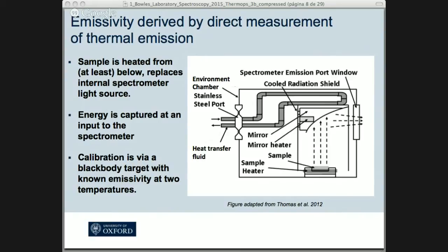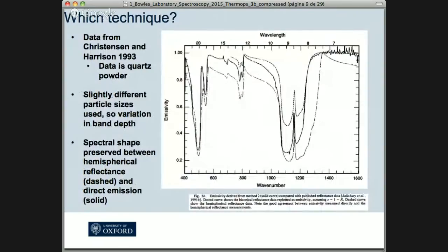And you control the thermal environment very accurately by having a temperature-controlled thermal shield around it to calculate out the downwelling radiance, and they also calculate the instrument response function using two temperature black body targets of known emissivity that you replace with the sample. So you continuously calculate and calibrate. So which method is best?